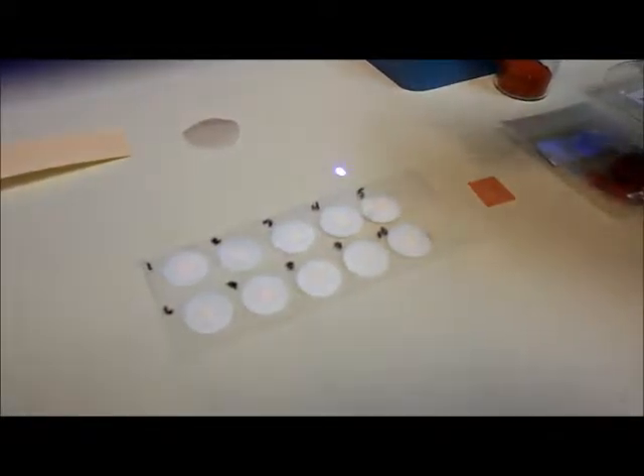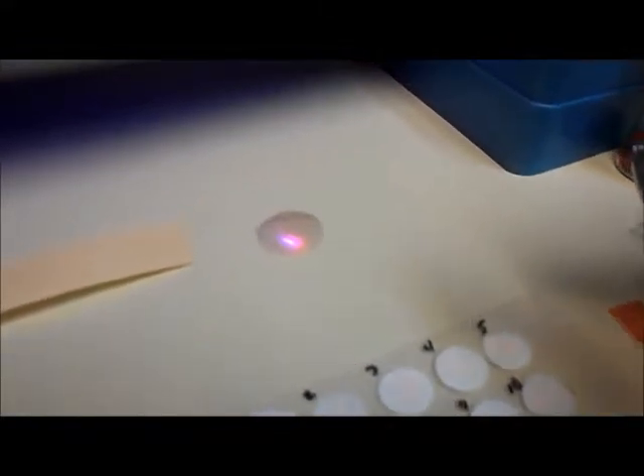And these are some little dots that we've made that are oxygen sensing, and we have another one over here, which is a different material, different type of application where it's sensitive to a very low level of oxygen and air. There's not much of a response to it at all. For a quick demonstration, I'm going to show you now this other matrix that's coated with the thin layer of the oxygen sensing dye. And we'll turn the lights off, and under ultraviolet you can see there's a little background fluorescence to this particular material, which I wanted to show the modulation.